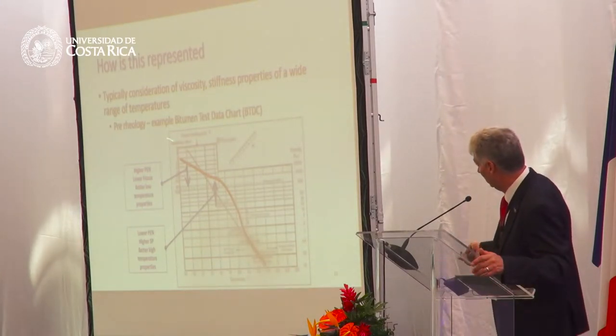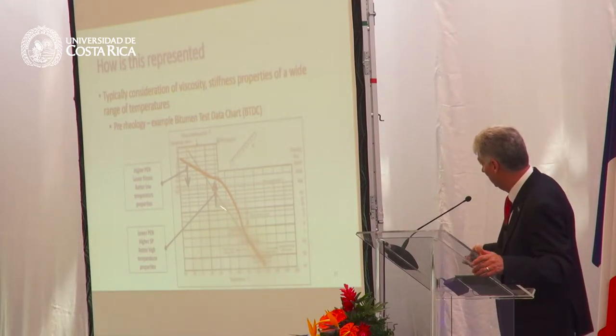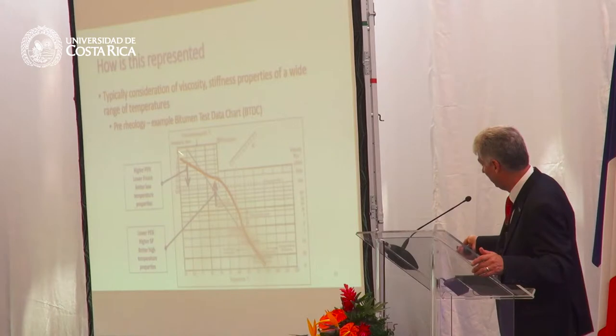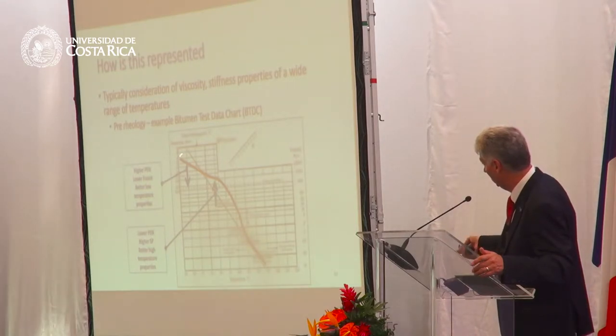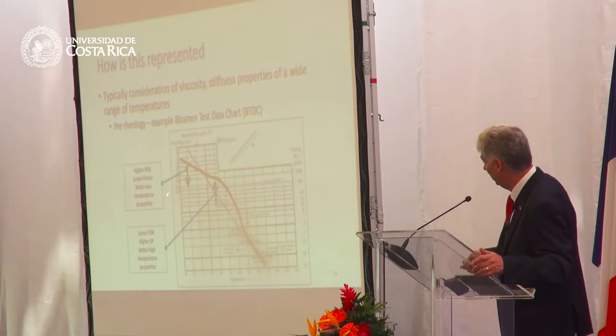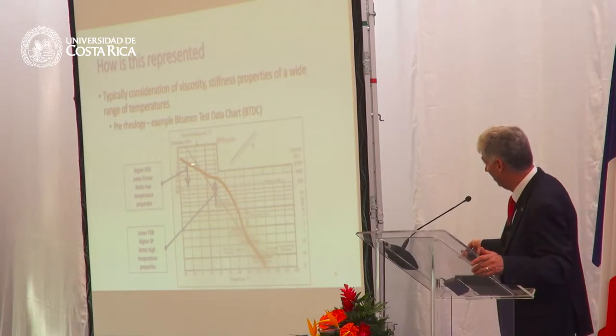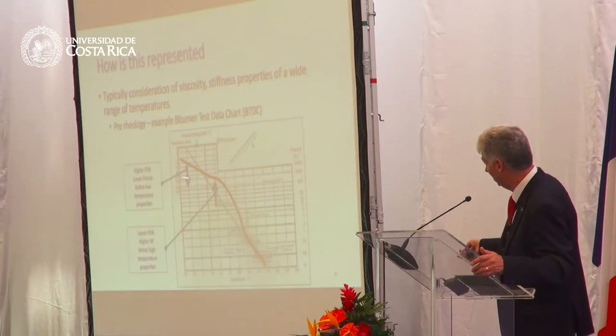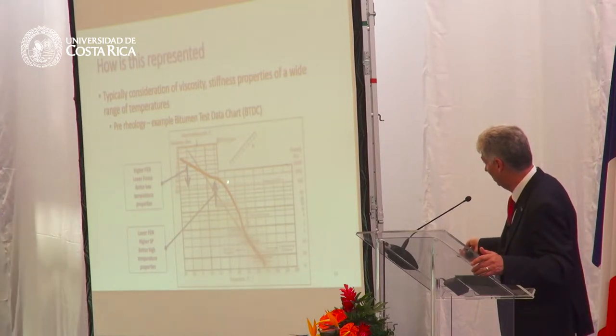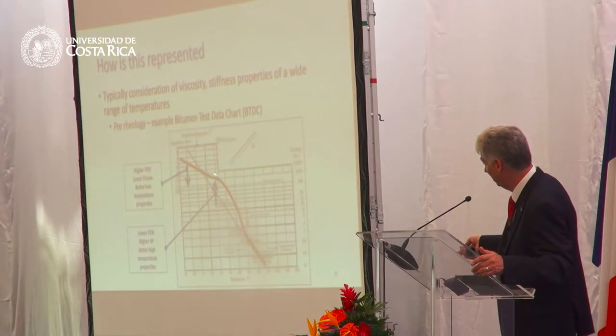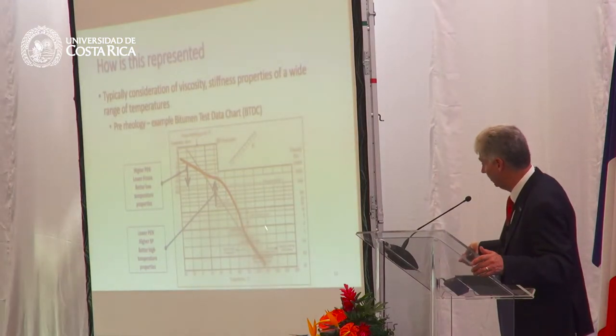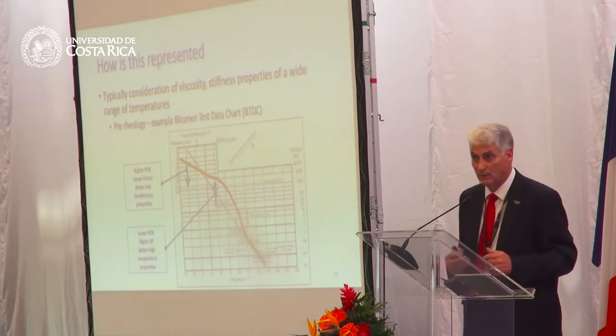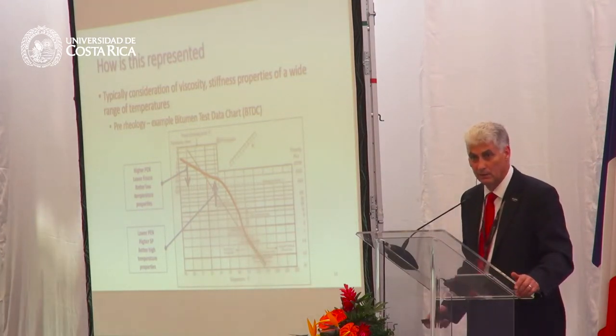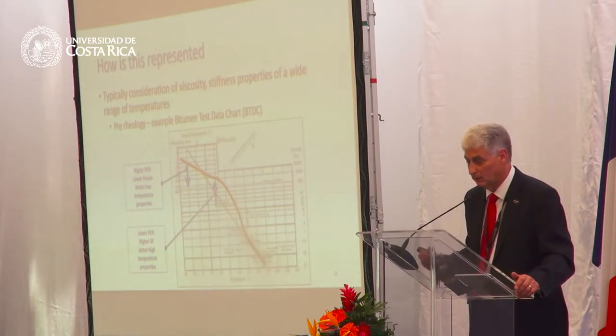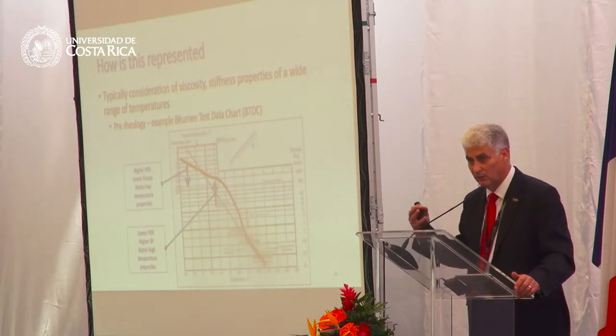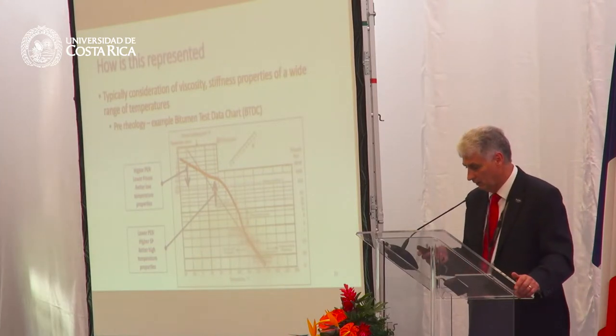And if you look at a chart like this, a typical bitumen will have a slope, a diagonal slope going across the chart. And ideally what we want to do with modification is flatten this part out, keep this part still a bit steep, so this part will be good for low temperature performance. Here's your rutting and deformation performance. And then you want to drop the viscosity so you can mix and compact. That's sort of an easy way of explaining it prior to the use of dynamic shear rheometers and rheology. But we want to achieve the same type of properties with our new testing and our rheology.